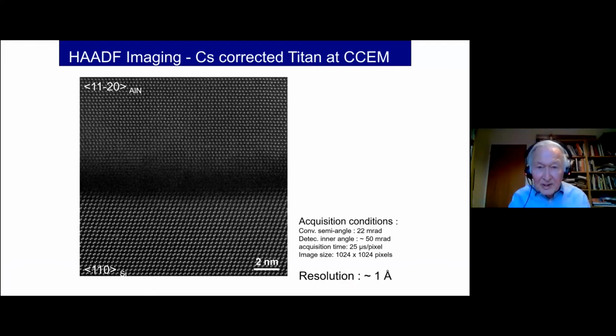And really unexpectedly, when we put this in the electron microscope, we saw this amorphous layer, which turned out to be silicon nitride, between the aluminium nitride and the silicon. And optimizing that amorphous layer was really important. In fact, if you lower the growth temperature, you get an abrupt interface. So this amorphous layer is due to interdiffusion of atoms across the boundary, across the interface, when you're growing at this very high temperature. So optimizing the growth conditions was really important for the quality of the aluminium nitride and the quality of the LEDs. So that's one problem that had to be solved.